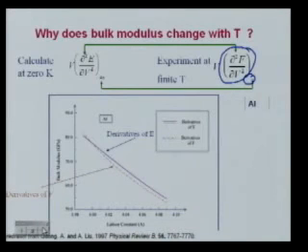What we do is, you don't have the free energy. Well, the energy is equal to the free energy at 0 temperature. So first of all, you take the second derivative of the energy, not of the free energy. And you don't take it at the finite temperature lattice parameter. You take it at the 0 temperature lattice parameter. Okay? So we have two sources of error. And they both require a different solution. We use energy to calculate the bulk modulus at 0 temperature rather than free energy. And we use the 0 temperature lattice parameter rather than the finite temperature lattice parameter.